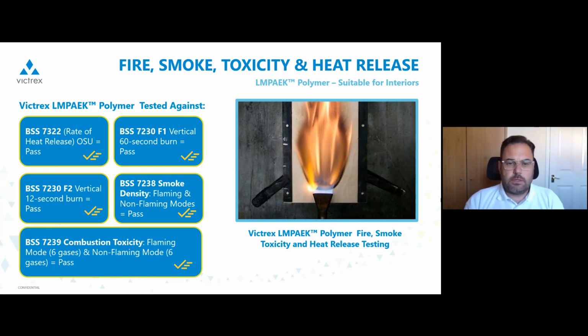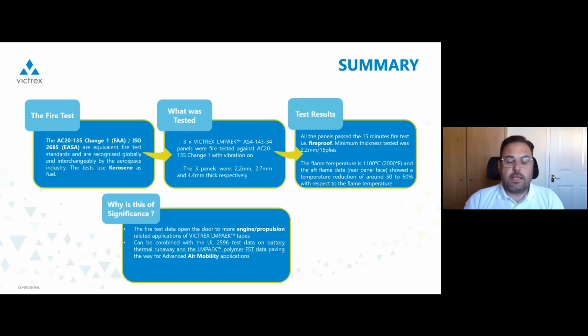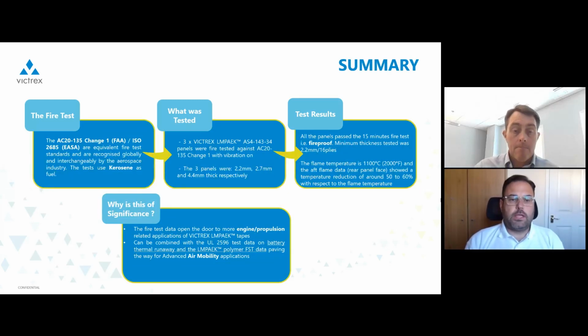Next one, please. Yeah, and that's my summary. So we tested against the AC 20-135, the FAA standard, which is practically speaking equivalent with the ISO standard. We tested 3 panels, 3 different thicknesses. Everything passed. Our material is fireproof. The minimum that we tested is 2.2 millimeters, the thinnest that we passed.